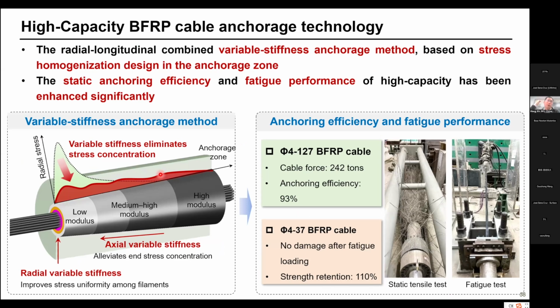Similar to the CFRP, we also did a lot of study on CFRP cable, but here we just show the BFRP cable. We use a kind of variable stiffness material to anchor the FRP to avoid stress concentration, especially not longitudinal, but the transverse directional compression on the fiber itself. Otherwise, it can only achieve maybe 60% or 70% of its strength. By these ways, we can achieve more than 90% of its strength, this anchoring efficiency.